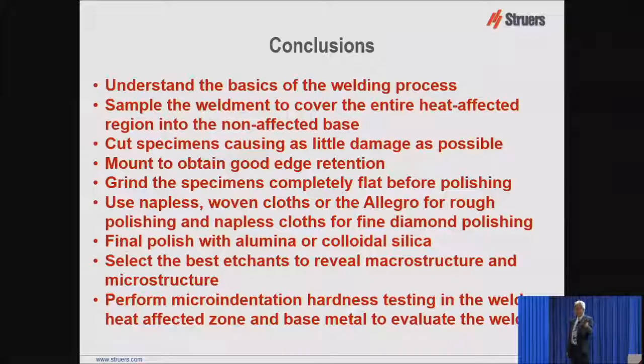If you're doing Brinell testing with 3,000 kilograms, a little bit of damage on the surface doesn't give you much trouble. But when you're in the nano range, that damage will destroy your data. And that is a serious problem.